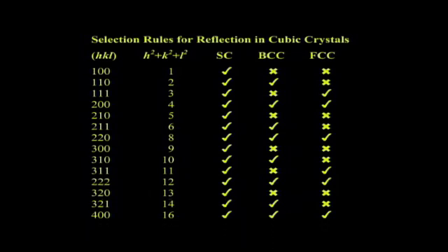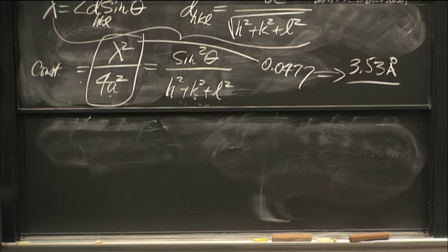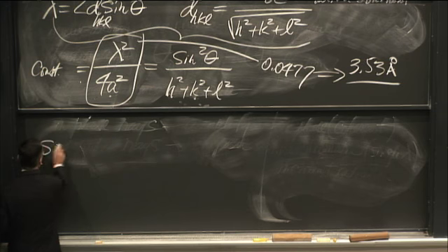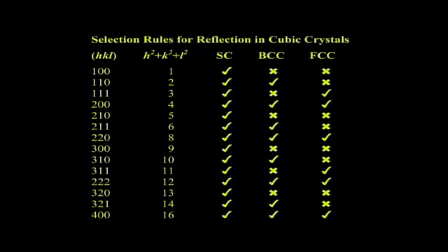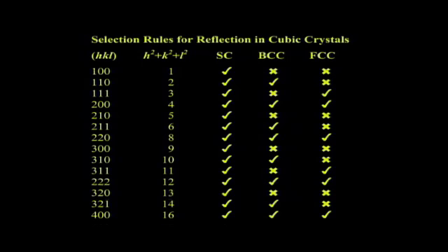Now, here's a little trick. Let me show you. Because when I go to index this, the first thing I do is I go for low-hanging fruit. See, if you start looking for whether it's simple cubic, face-centered cubic, body-centered cubic, let's look at the sum. All right, so I've got simple cubic, body-centered cubic, and face-centered cubic. So the first plane on simple cubic, it's going to give me everything, right? It's going to give me 1, 2, 3, 4, 5, 6. And FCC, what does it give us? If you start looking down there, it gives you 3, 4, 8, 11, 12.